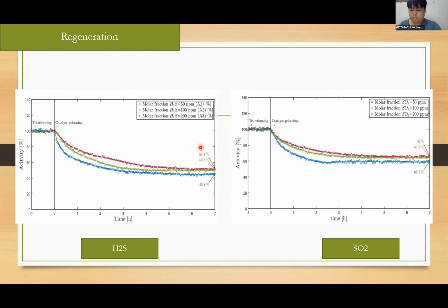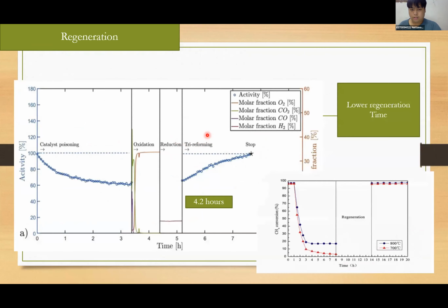The result of sulfur poisoning showed that the deactivation was caused by sulfur chemisorption from hydrogen sulfide and sulfur dioxide, but hydrogen sulfide has more effect than sulfur dioxide at every content. And the regeneration results show that it spent about 4.2 hours in the regeneration step. That is lower than steam treatment.